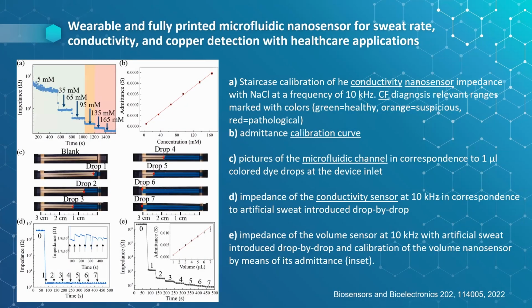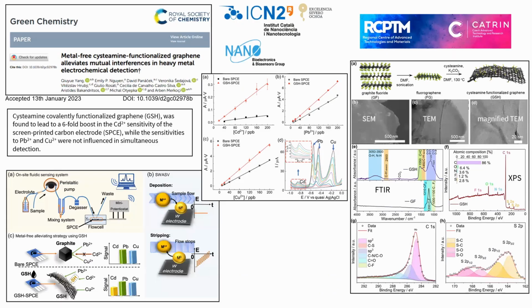And with some typical measurements, for example, showing impedance, or electrochemical measurements for different kinds of parameters that we are interested in. So either for conductivity, but also for copper concentration using electrochemical stripping, where you can see the different signals obtained using different kinds of procedures. So usually we use electrochemical stripping, but also impedance measurements.